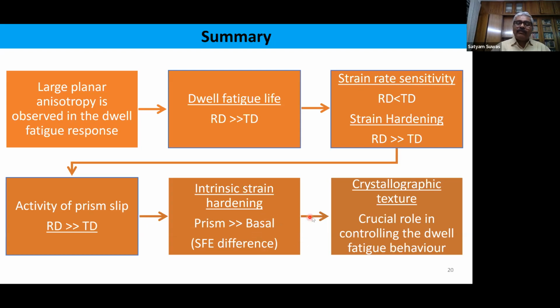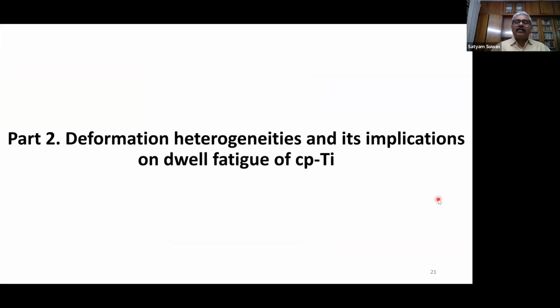And therefore, this whole thing clearly tells that texture plays a crucial role in controlling the dwell fatigue behavior. So basically, we have not changed different types of texture, but we have just extracted samples along different directions, which essentially represents two different types of textures. Particularly, the planes are the same, but the directions are different, and therefore it indicates that the dwell fatigue phenomenon is texture sensitive.